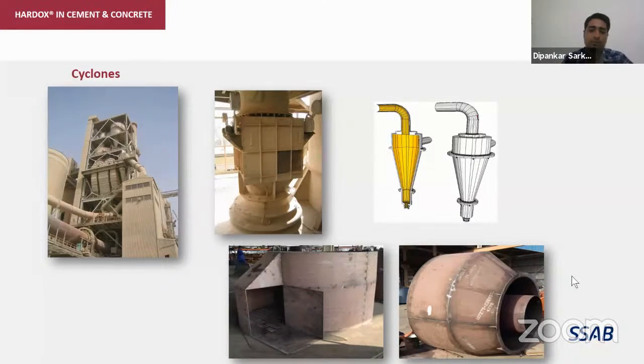Later on in the cyclones, it becomes around 900 degrees, which is quite hot for Hardox. And in that, there are some other solutions. Wear liners in the cyclone walls made from Hardox are extremely strong, and not only strong, they can reduce the weight, and that helps a lot in the maintenance stops to change the liners. Next slide, please.